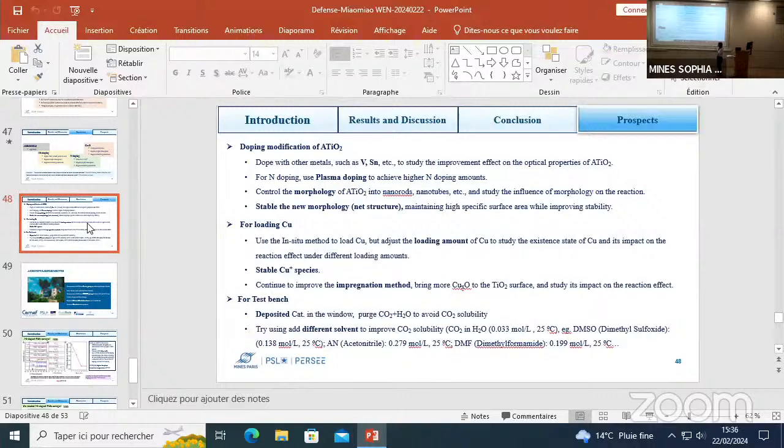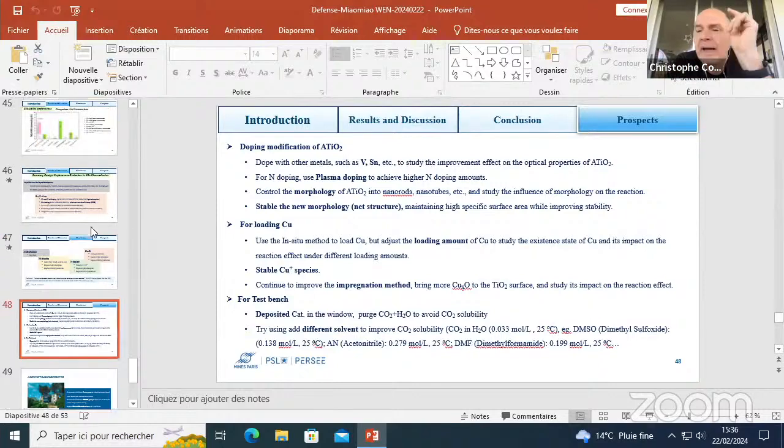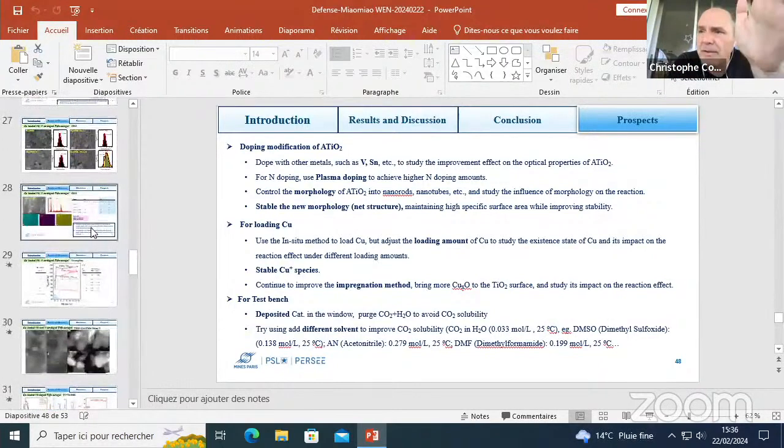So the direct way is working on its valence band and conduction band. For the conduction band, it's better to choose metal doping to generate a new CB, and non-metal doping is to generate a new VB. I understand the principle of each one, but why niobium and not chromium, for example?